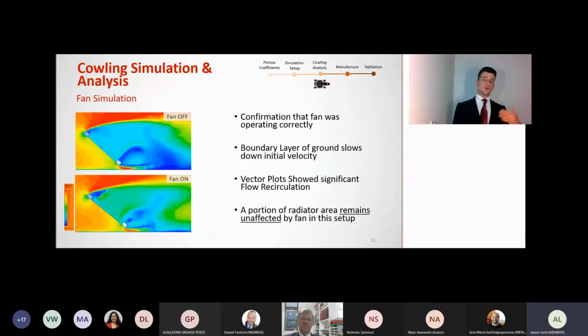Post-processing was done on simulations both with and without the fan. This was done to compare both models and to ensure that the fan was operating as expected in the model. In all simulations to follow, the velocity and static pressure were the variables of interest. And when observing these contours, the effect of the fan on the flow through the radiator is visibly significant. And this was enough to confirm that the fan model was indeed working correctly.